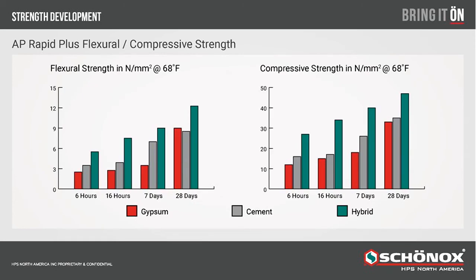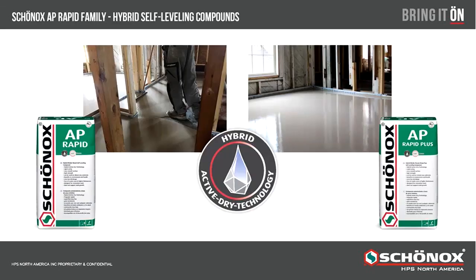So look at your flexural strength and compressive strength as well. Gypsum systems normally take a longer time to get your initial flexural strength, up to 28 days, and continue on that scale upwards. If you look at the cementitious product, it's the same way, but you're also getting a higher compressive strength on the cementitious side as well. The hybrids that we have get higher flexural strength in a shorter period of time, and also a higher compressive strength in that shorter period of time as well. So that's giving you easier workability, able to go over these critical substrates, and able to put your final floor covering on them in a much shorter time frame.